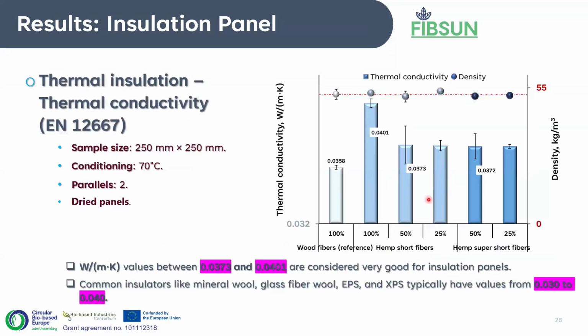Then the main point, which is the thermal insulation and thermal conductivity, as we already saw, as I pointed out from the crystallinity index, that it's more likely the wood reference would be better in this regard due to the low crystallinity index, and we see that from the final product. What we notice is that with 100% incorporation, there's a huge change in thermal conductivity. In the case of 25% and 50%, we didn't see any real difference. And actually, for all the hemp biomass, they behaved about the same.